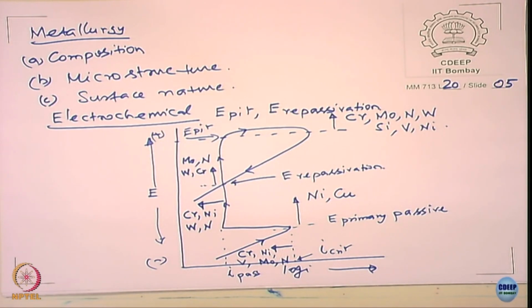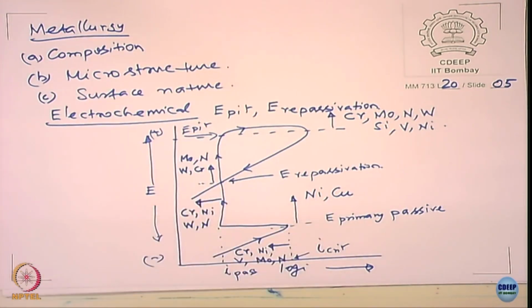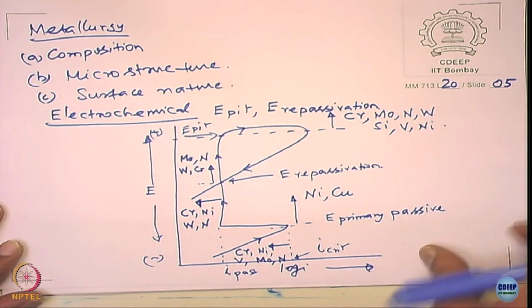Of course, you cannot keep adding the way you want. Suppose I take an austenitic stainless steel, I want to increase the pitting resistance, I cannot keep adding so much chromium, right. If you add it, what happens? The austenitic phase will turn into a ferritic phase, okay. So then you need to make a phase balance, so you need to add nickel to it, right. So the alloy development is a different story altogether, but the corrosion resistance story depends on this diagram, okay, and in order to get different phases you compensate with the relevant alloying elements. That is a different story of physical metallurgy of stainless steels, we will not be discussing it here.